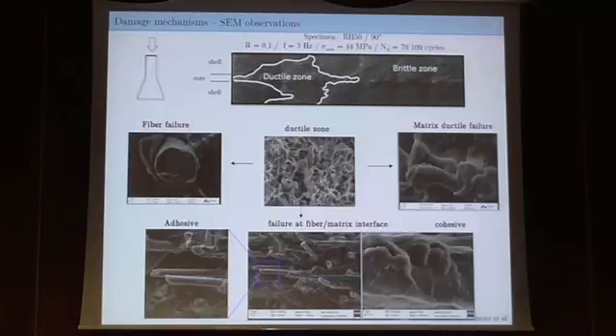of the surface, and you can see some different damage mechanisms: fiber failure, matrix ductile failure in some area of the specimens, cohesive or adhesive failure of the matrix and the fiber interface. But if you do this, you have no idea of the kinetics. You have no idea of how much fiber failure I have in my materials.